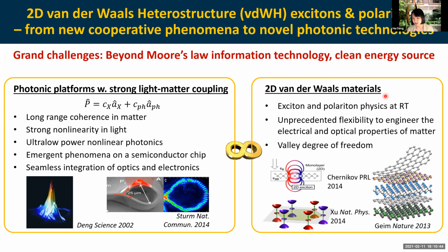They are called van der Waals materials because they form covalent bonding between atoms or molecules inside each layer, but between the different layers there are no dangling bonds. They are like perfect crystals with no hanging-out electrons, so they can only bond through the van der Waals force.